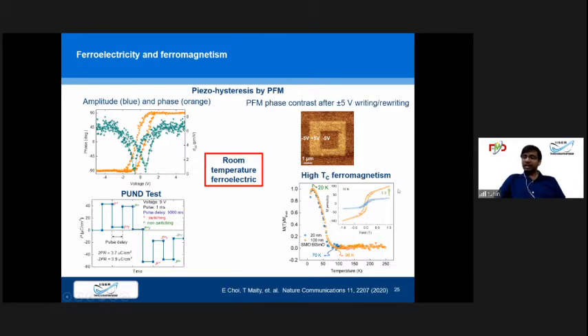So that means this material has become room temperature ferroelectric and low temperature ferromagnetic, which before was not room temperature ferroelectric and was low temperature antiferromagnetic. So no ferromagnetism was there at this temperature.